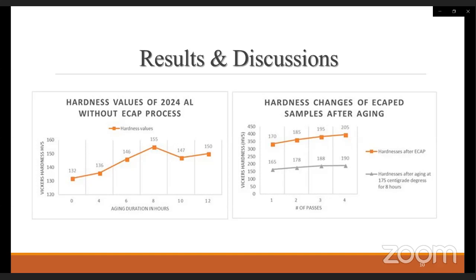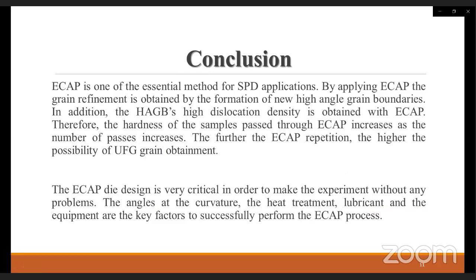The hardness values of samples as solutionized are 132 Hardness Vickers 5, and the hardness values of the samples which are not ECAPed but aged at 175 centigrade degrees for 4, 6, 8, 10, and 12 hours are given on the left graphic, and the hardness values of the samples after ECAP plus aging are given on the right figure. Okay, so as we can see, the decrease in the hardness for 1 pass is 5. For 4 pass, it is 15. So let us pass through the conclusion.